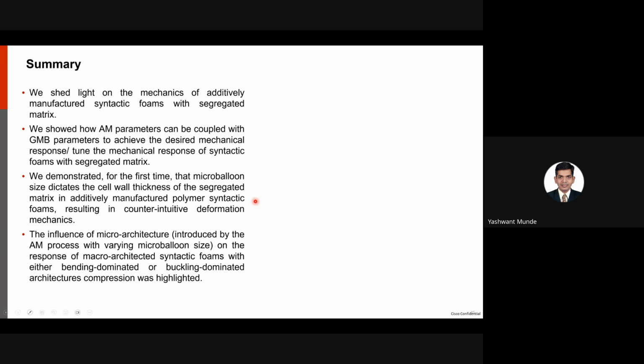thickness, and also decides whether we have a stiffer or a high densification stress in these syntactic foams. The influence of microarchitecture on the macro-architected syntactic foam, that is how embedding these micro scale particles manifest differently when we choose bending dominated versus buckling dominated architectures under compression.